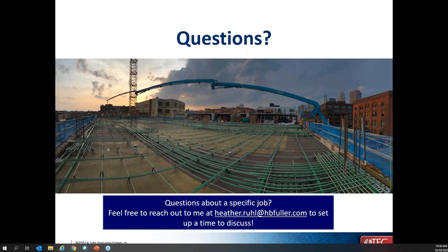Yeah, so that's especially true when you're talking about MVER, again, those calcium chloride tests. One of the reasons we've really leaned towards and really started recommending installers start using the RH meters or the RH probes is that I don't think that there's a calcium chloride test that actually gets left undisturbed for the 3 days that it needs to get an accurate reading. So to that point, RH meters typically are a little bit better about not getting disturbed and, again, not having issues with site conditions. And again, they're not normally as affected by the ambient conditions. I will say that is one of the reasons why we recommend multiple tests, just in case something does happen in one of the test locations, you don't base all of your assumptions off of a test that might or might not be accurate based on the site conditions.